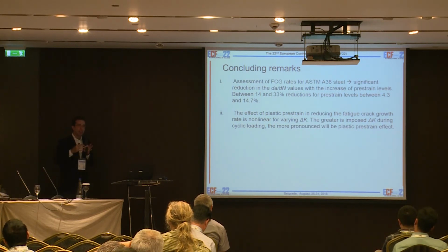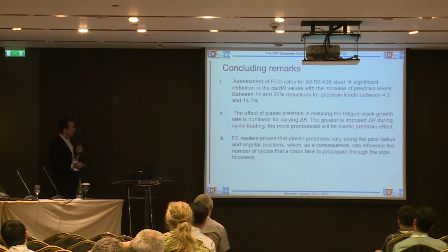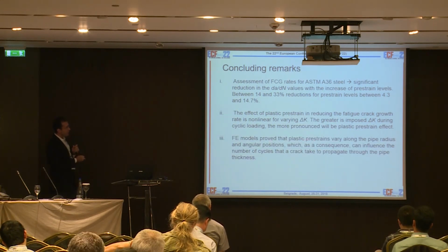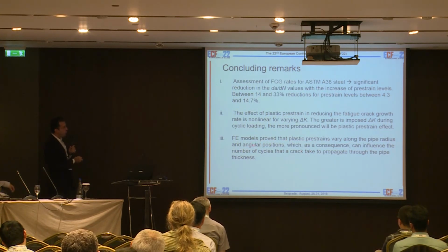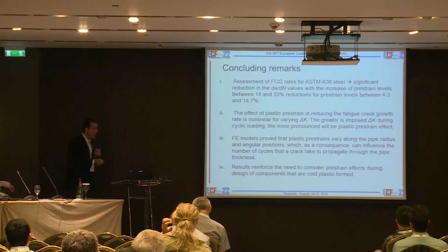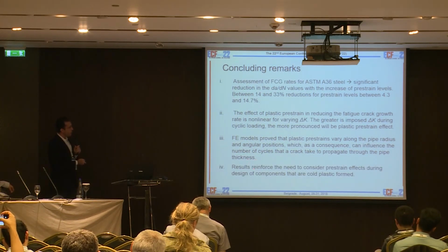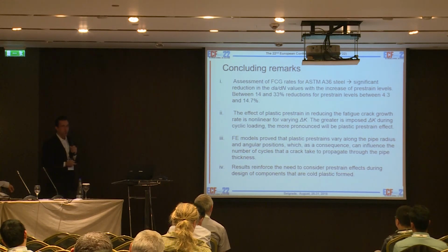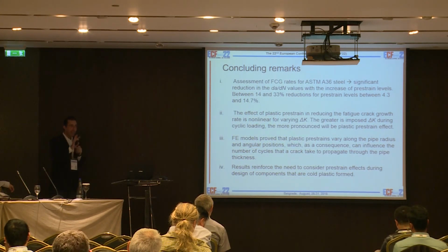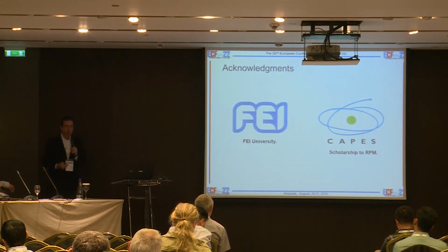In our case, as there was a pipe with a relevant thickness, triaxiality was already included, but if you have applications of varying triaxiality, take care. The FE models proved that the plastic prestrains vary with radial and angular positions, and the results I presented here reinforce the need to consider prestrain effects during design of components that are plastically formed. If you can consider constraint also, it's a good deal, and in real applications, just to give you an idea, we had deviations that were around 20% to 25%. So it's kind of relevant stuff.